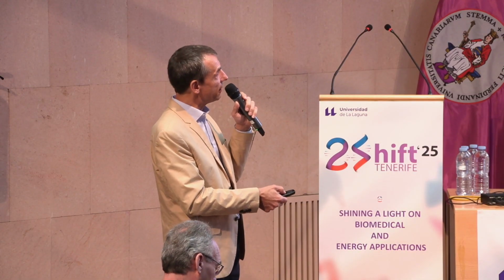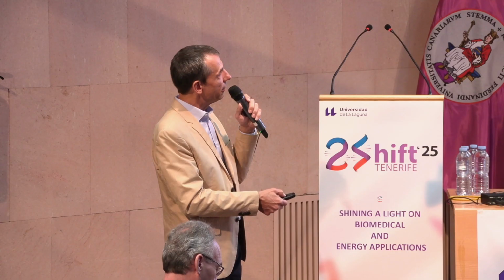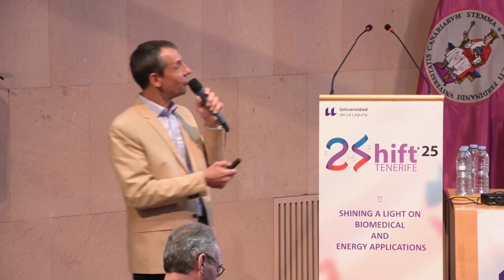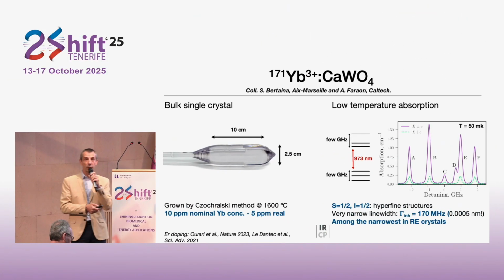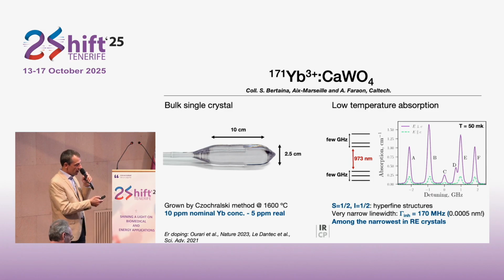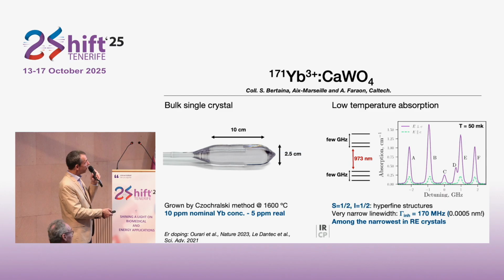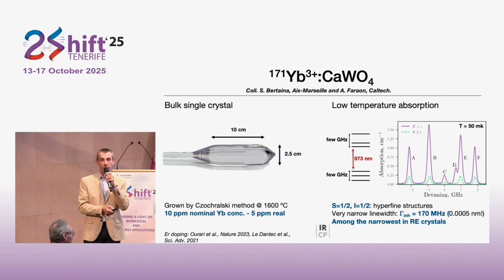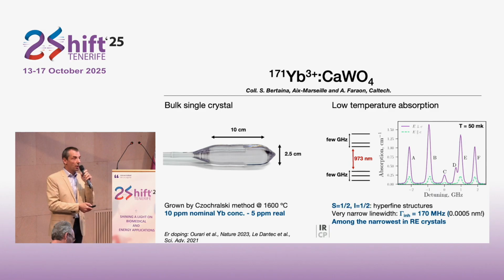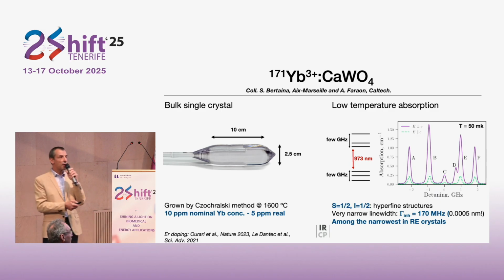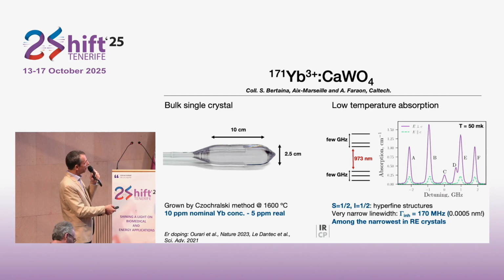Well, of course, it's because the lines are extremely narrow. Here in this frequency scale, it's 170 megahertz, but maybe if you are not so familiar with these units, which are usually used in high resolution spectroscopy, this corresponds to 0.0005 nanometers. So it's really extremely narrow. And this is why we can still get significant absorption, even though we do not have so many ions in the material. These line widths are among the narrowest observed in rare earth crystals. Many materials exhibit at least 10, maybe 20 times broader optical line widths.